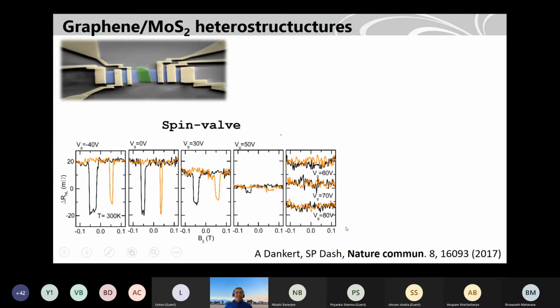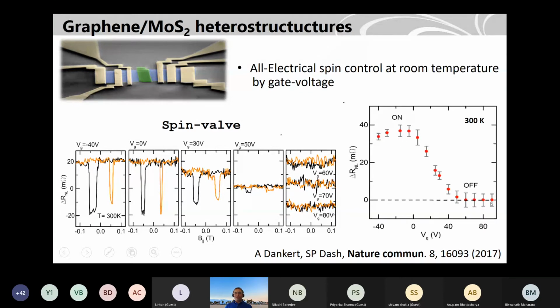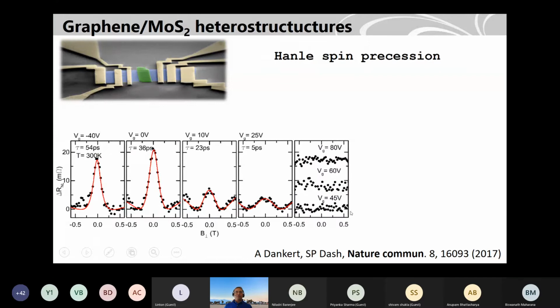And most interestingly, what we see is that when we apply a gate voltage, we can reduce the signal. That means it's tunable, and the signal magnitude can go down. And this is like an on and off. So it's not a spin transistor, but you control the spin signal in some way.